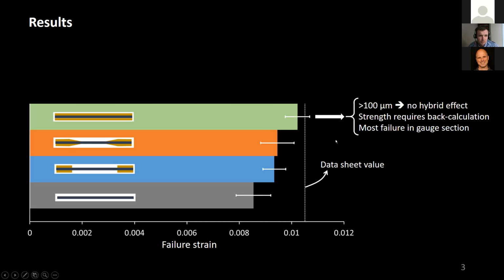A few things important to point out here. Our plies were well above 100 micrometer, which means there is no hybrid effect, at least if you correct for the thermal residual stresses. The difficulty is that this is actually not a technique that you can directly measure strength, because that strength requires a back calculation, which introduces some additional error. So that's why it's better to look at the failure strain in interpreting the data from this type of specimen.